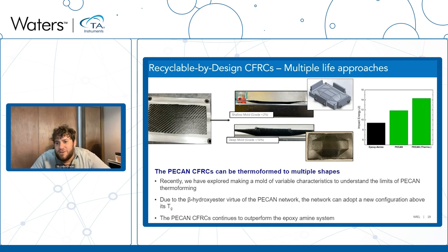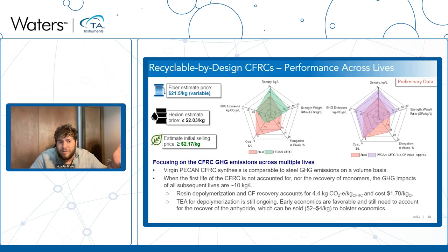Also, we've shown that the redesigned material has better impact energy than the epoxy amine baseline. And when you thermoform the material, like in the vehicles industry, you can get better impact energy. So I showed you in the second part of this talk that we're able to redesign materials using bio-based materials to be recycled by design and have better performance. NREL is an analysis-driven lab.